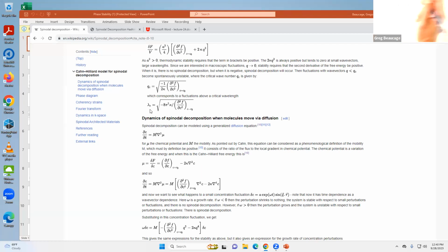And also for one reason, you have to square it because you're going to get total free energy over here. Total free energy is going to be the integral of this volumetric free energy. This is the actual free energy for the sample that you have, and this is per volume. And there's this kappa for the gradient, and the gradient is going to be judged by this thing, but you can't have that because that's a vector, so you have to square it. So you have to square that guy, and then dV. So that's that first equation.